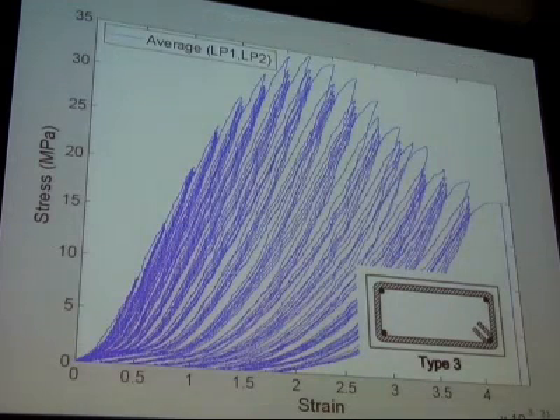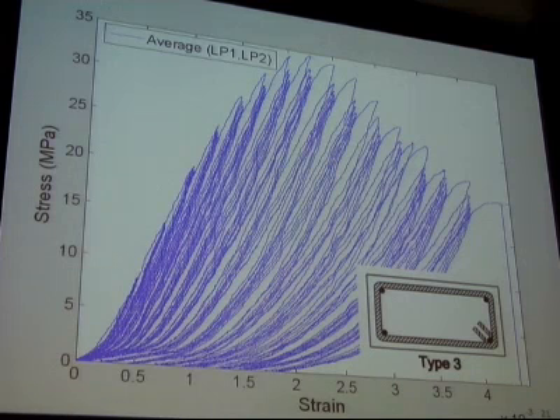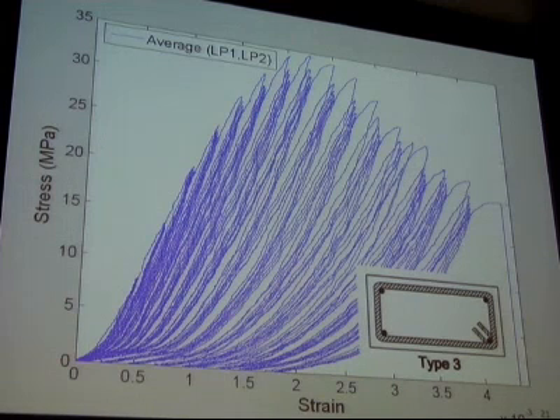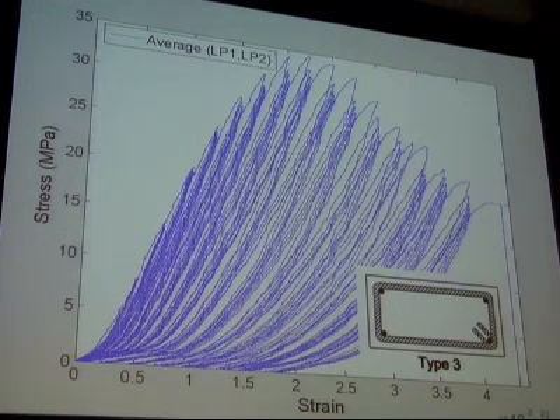And here's exactly what you might expect. The type 3 elements, the response looks like a concrete cylinder response. You get out into strains of 4 parts per thousand before it finally crushes. And even then, it's quite reasonably ductile. So very nominal ties, very light ties, makes it behave like we sort of hope it would. And these elements are in pure compression.